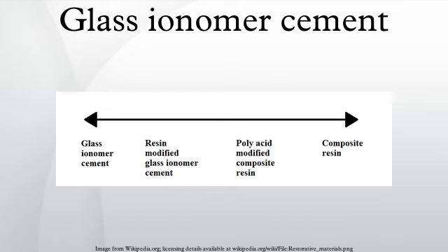Advantages: intrinsically adhesive, fluoride release, but this does not guarantee freedom from secondary decay, similar coefficient of thermal expansion to tooth. Disadvantages: considerably weaker than amalgam and composite, tendency to crack worsened by early instrumentation. Silver-containing materials offer little improvement in physical properties, some materials radiolucent. Recommendations: excellent filler but relies on having sufficient dentine to support crown.